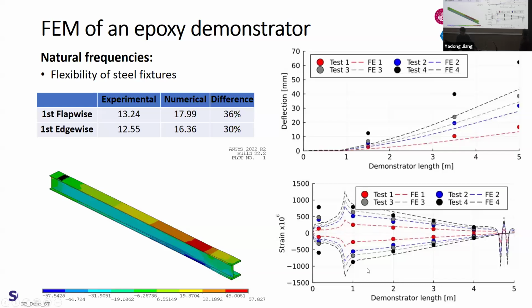But if we take a look at the strain, you will see that for all the load cases, all the strains agree well with the prediction. The only exception is the strain on the root parts, because the root parts are very complex. You have your adhesive, you have your steel inserts, so it's very hard to predict the strain around the root parts. But apart from that, for all 4 load cases, we have good agreement. That means there is no damage in the composite parts, and the weakest part of the demonstrator is the constraint system.